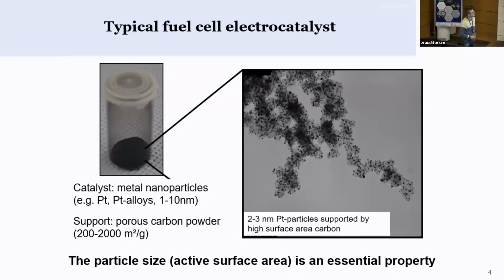And in order to guarantee that the surface area is maintained, you put these particles on a support, which needs to be electron conducting. In applications, that's basically carbon powder that you see here. So you have a high surface area carbon with surface areas varying between a few hundred and up to 1,000 square meter per gram, onto which you support these small particles.